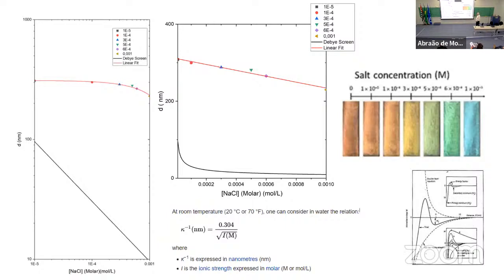This is a mystery. I said that we get these bright colors because there is a fixed distance. There's some interaction between the clay platelets. So that makes at least some domains, typically 10 to 15 clay layers in each domain, the fixed distance between them. And we don't quite understand what controls this distance. This is something we're working on.